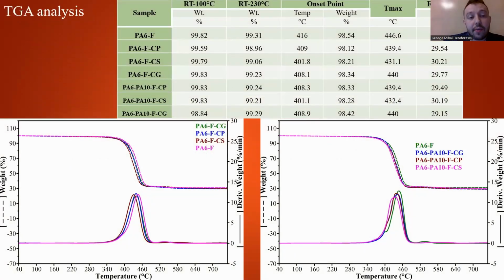The thermal analysis revealed a similar thermal stability for the 2 series of samples compared to polyamide 6F until 230 degrees, which is the temperature at which the composites were processed. The table shows that up to 100 degrees, the loss of mass is insignificant as a result of the drying process of the materials before processing. And this aspect is particularly important in the case of polyamides, such as polyamide 6, because this polymer matrix has very strong hydrophilic behavior. And after 400 degrees, the samples start to decompose, all having the same thermal behavior, a single decomposition step, as you can all see.